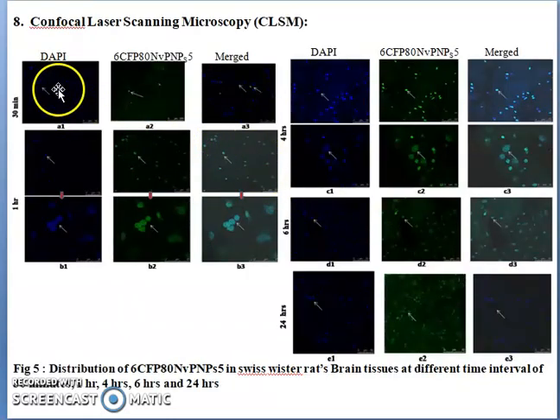Now when it was observed with CLSM, this is DAPI for staining the cell tissues, and this is 6-carboxyfluorescein for nanoparticles. When it is merged, we found that initially at 30 minutes less concentration could reach the brain. With increasing time, the highest fluorescence intensity was observed at 4 hours, and this is similar to the previous result, that in 4 hours maximum concentration of drug was obtained, that is Cmax. So this satisfied those results.